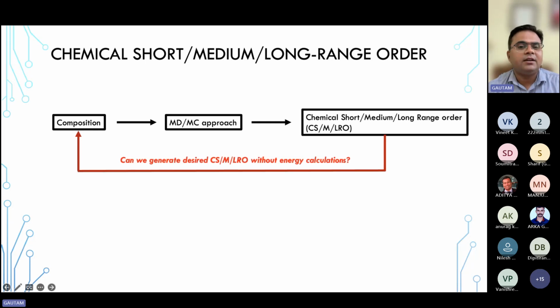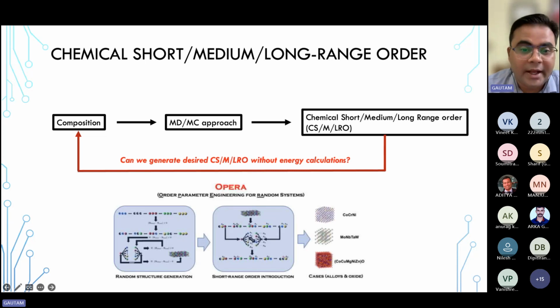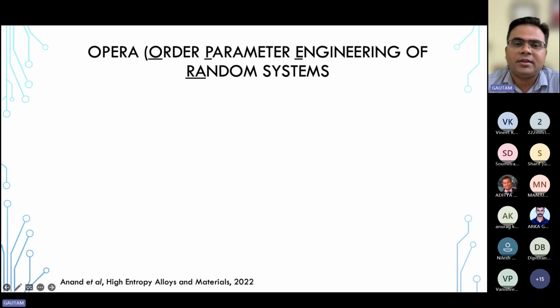Can we generate the desired configuration without energy calculations in the first go? Because you want to develop a high throughput method. And yes, you can. With the OPERA approach, which we have recently developed, you are able to generate the chemical short range order in these kinds of alloys. You start with a random structure, you can generate short range order, and we have applied this to alloys as well as high entropy oxides. So OPERA, or order parameter engineering for random systems.